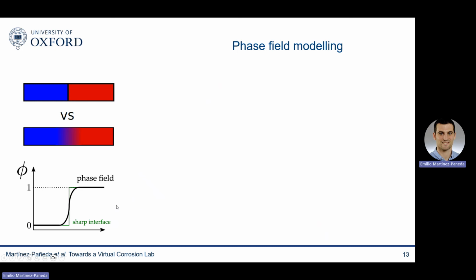However, the good news is that a new technique has been recently developed that enables tackling interfacial problems of arbitrary complexity. These are the so-called phase field models. The idea is quite simple. Instead of describing the interface between two phases, such as aqueous electrolyte and metal, as sharp and discontinuous, you can smear that interface over a finite domain and use an auxiliary variable, the phase field, to describe where the interface lies. And then you just need to define a differential equation for the evolution of this phase field.